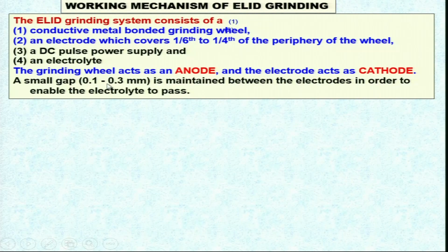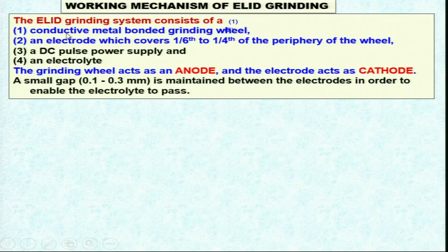The grinding wheel acts as an anode, which we normally call the workpiece in the case of electrochemical machining, because material is being removed. Here also the material is being removed from the grinding wheel, so that the fresh diamond abrasive particles protrude, those which have borne out already, and once they are borne out, because of the larger force they are separated out from the grinding wheel, and the electrode acts as a cathode. A small gap of 0.1 to 0.3 millimeter, that is 100 to 300 micrometer, is maintained between the electrodes in order to enable the electrolyte to pass. So, this gap is maintained between the external electrode and the anode. This electrode works as the cathode, and this grinding wheel works as the anode or the workpiece from where the material is being removed.